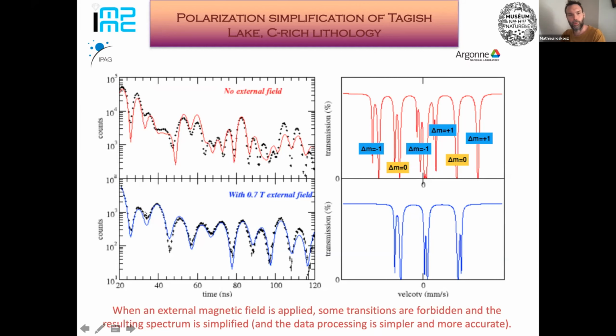We use this to determine the redox states of the grain, because it makes the magnetite signal less intense, so it was easier to deconvolve the contribution of magnetite and of clay minerals containing iron with different oxidation states.